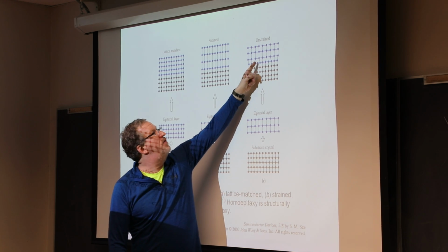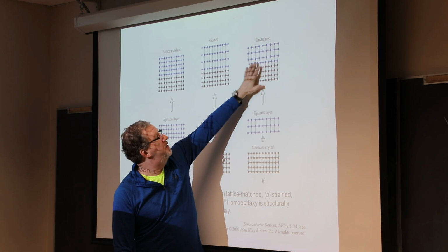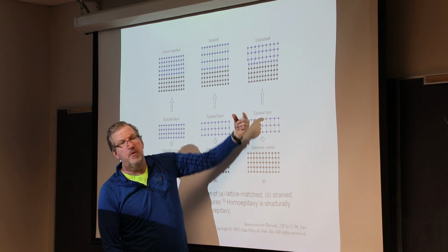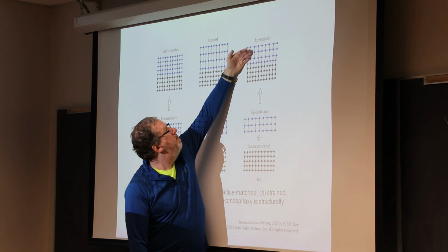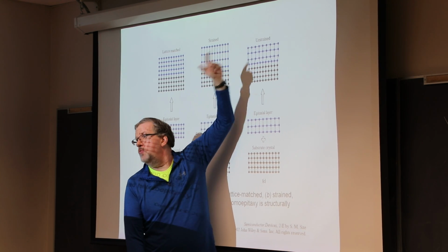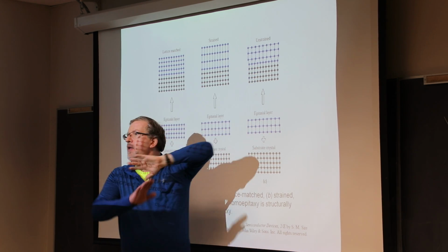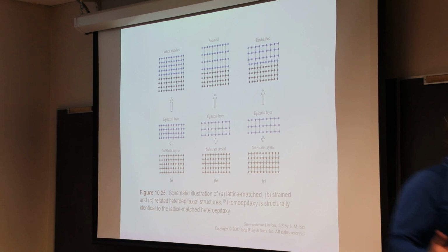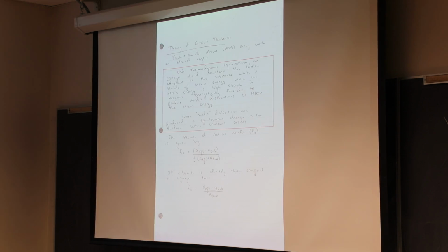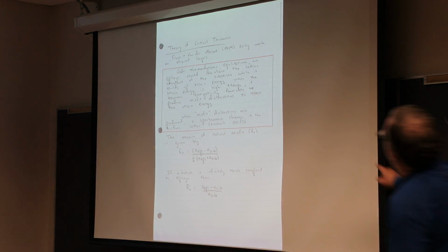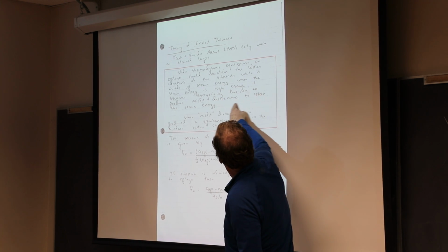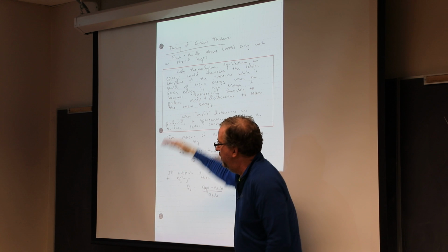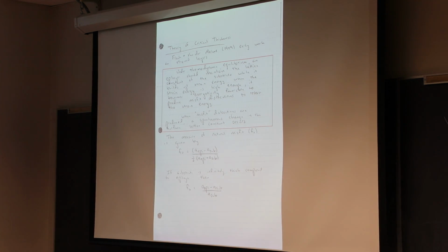row of atoms every so often, right? And so that means the lattice constant was too different, and the thickness got to be too large. It might have accommodated that strain if it was 1 to 2 monolayers thick, but once it got to be 3, the strain energy was too much. So the terminology I like is that it became energetically favorable to produce a misfit dislocation to release the strain energy. That's my preferred terminology, but you can use your own words.